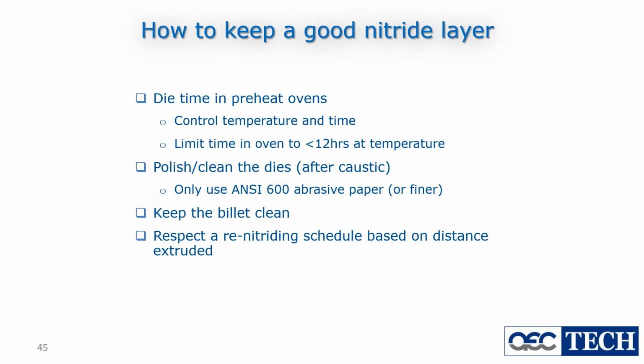But the regular testing of a cube of steel, and you can get these test pieces from most die suppliers that I know. They'll supply these either free or for a small charge, and then you put them in with your nitriding charge, also making sure they're clean, and then a lab somewhere can cut them up and investigate to see how good that nitriding was.